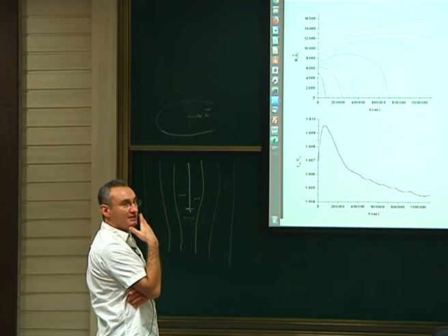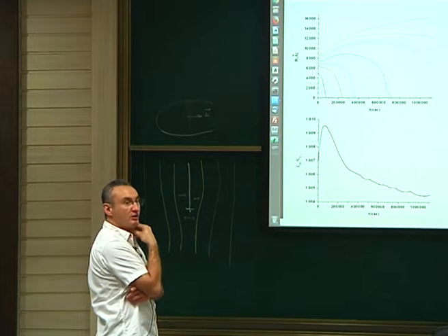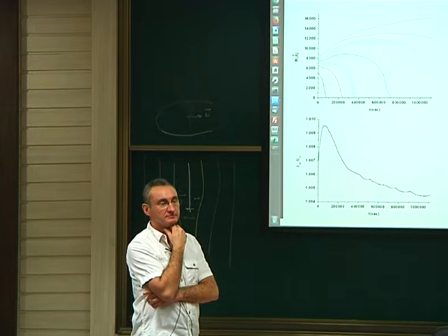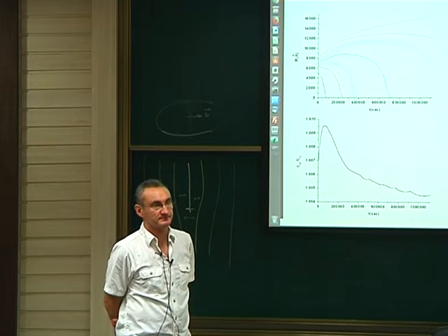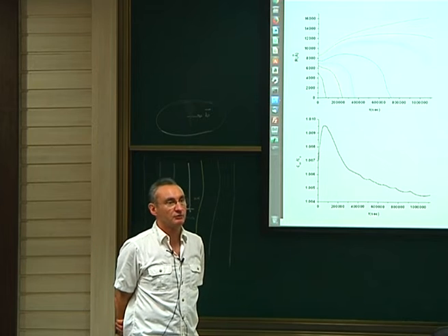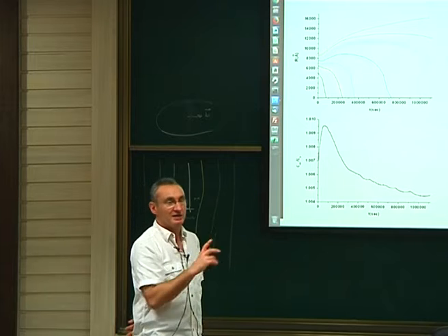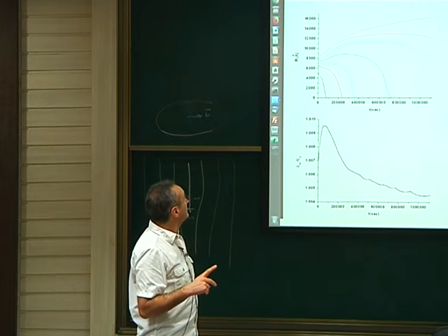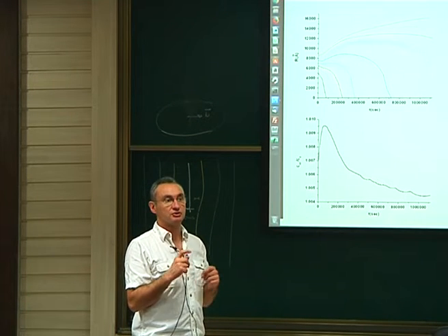That's a good point. I would say so, but I'm not sure. If you don't scale your vacancy concentration with temperature, then this... no, but there is the Arrhenius law anyway. There is the Arrhenius law in the velocity, where the temperature is explicitly there. If you think only about that, I think it will just shift it. Except that what is not true is that if you change the temperature, the climb force will not be changed. So the balance is not equivalent.